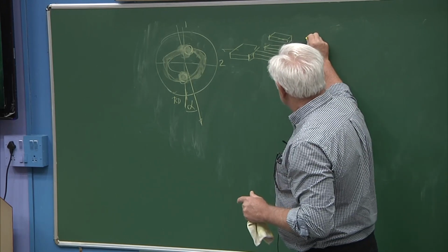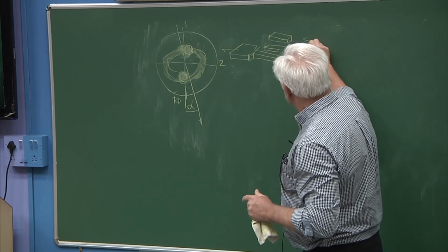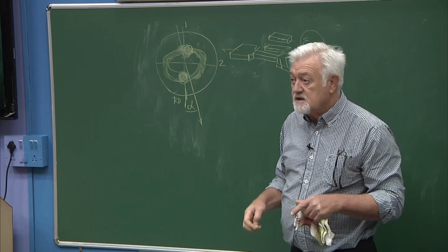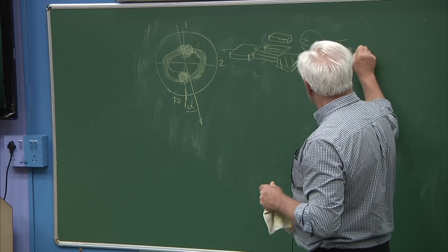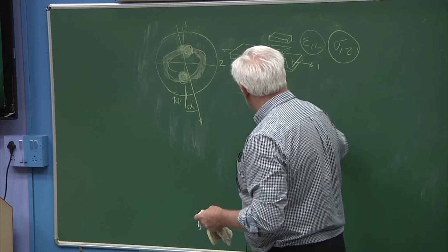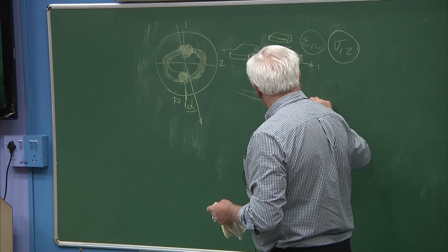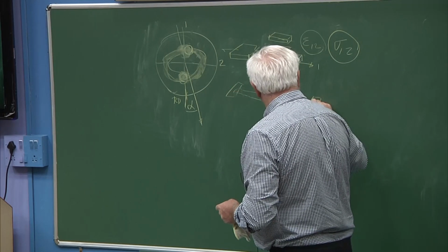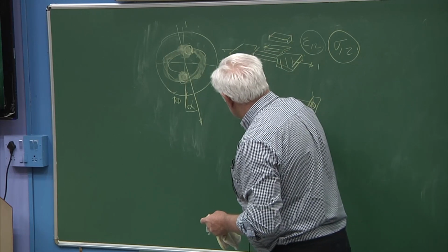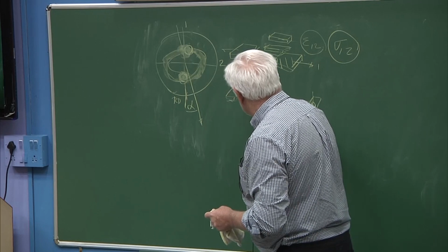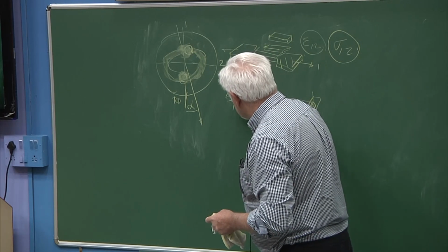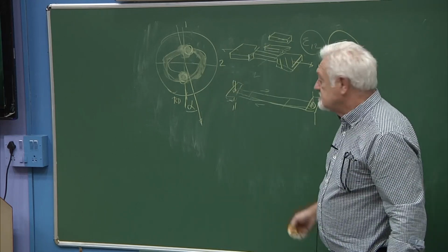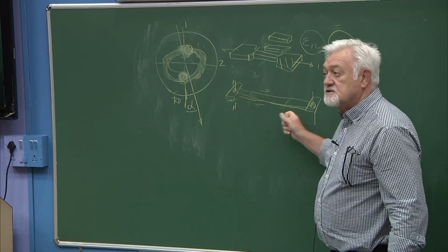This should be the shear epsilon 1,2. So this is 1, this is 2. So if you prevent the shear epsilon 1,2 from taking place, then you need a stress. There is going to be a sigma 1,2. On the other hand, if you have a very long sample, and you have pins here through the hole, and you pull, this part of the sample is going to shear like that, because it is not constrained by the shoulders.